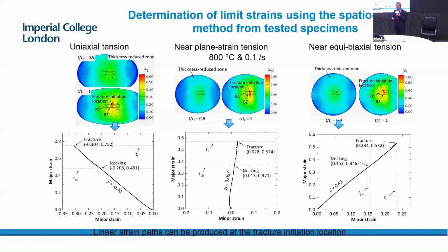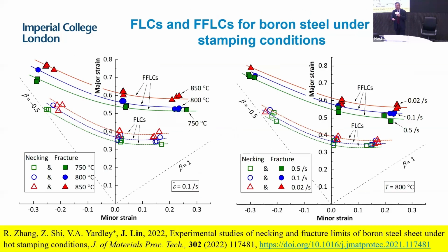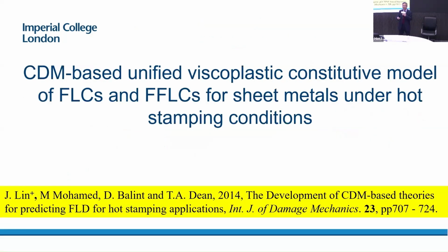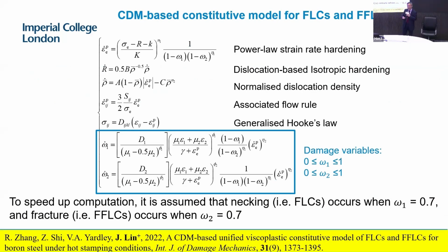Then we use the method to determine the necking strain and the fracture strain for different conditions, and then we plot the diagrams. We set the forming limit diagrams with the fracture limit as well, for different temperatures and strain rates for the boron steel. And once we get the data, then we can develop the equations for modeling. Again, for forming limit diagrams under hot stamping conditions, we are recognized as the first to propose a method, in 2014, to model this kind of behavior. And the method was specifically applied to boron steel in 2022, generating this set of equations.